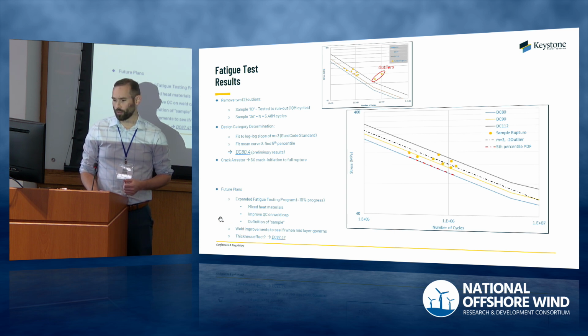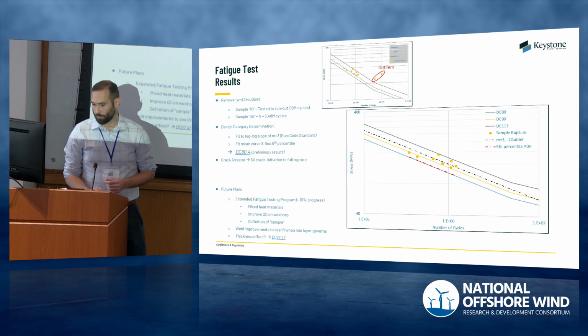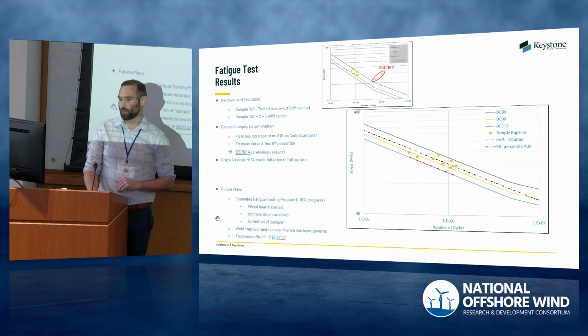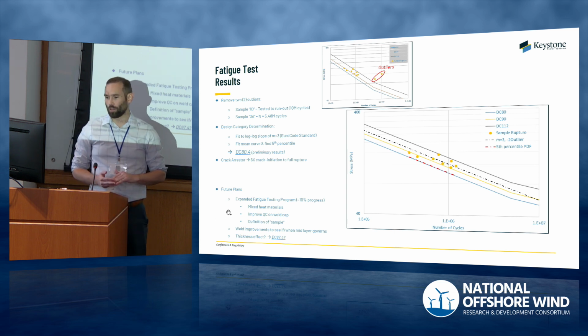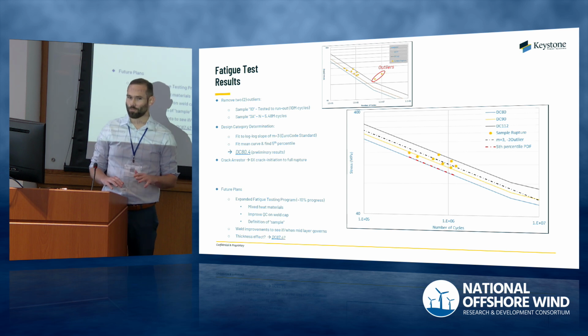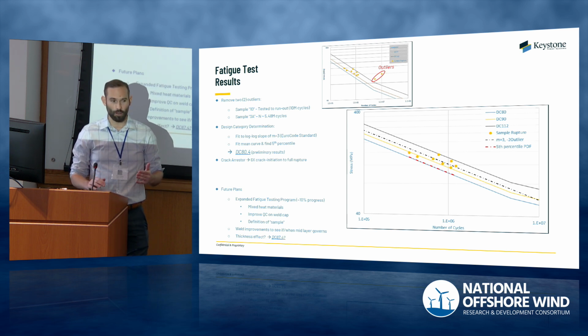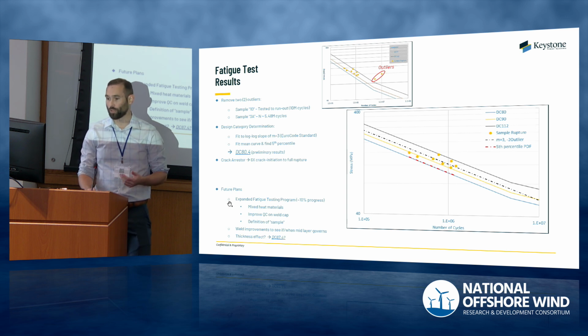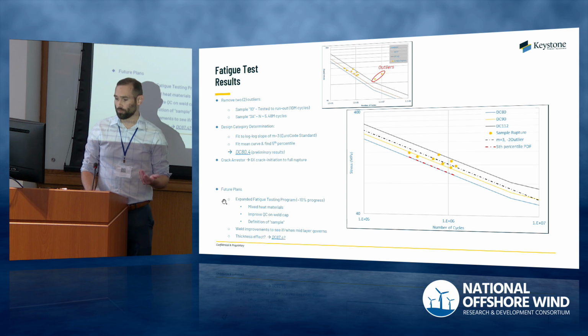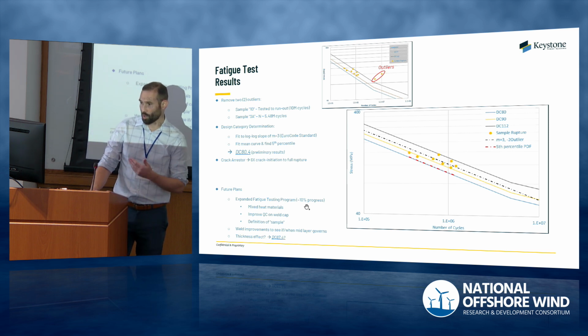We could do some better quality control on the weld caps, and it'd be interesting to treat the weld caps and see at what point the mid layer does govern, if ever. So, interesting results. Basically, the point of all this is to say, whenever we look at buckling, we're not seeing anything that would say this is a complete non-starter, that the technology should not be investigated further. We're saying it's worth looking at from a finite element model perspective, and some of the early tests are showing that those models might be accurate. The fatigue test results, while just the beginning tip of the iceberg, are showing promising results.